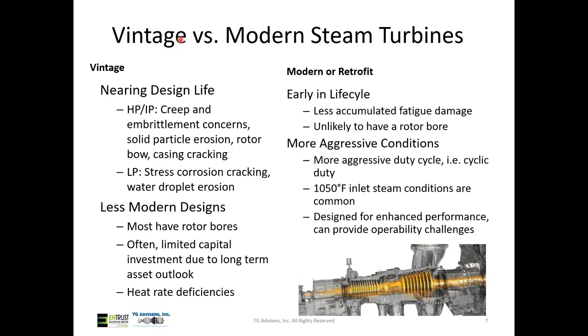All right. I alluded to earlier that we do have quite a variety of steam turbines still out there operating. I'm going to put them today into two categories. The first one being vintage. So we've got to be very careful with these vintage units that are still operating because they're nearing their design life. For the high pressure, high temperature rotors, that may mean that we have creep or embrittlement concerns, solid particle erosion. We may have a rotor bow that's developed, and we may have casing cracking. For the low pressure turbine, typically what we're worried about is stress corrosion cracking or water droplet erosion. So these are failure modes that are likely present, and we're having to manage in that vintage unit.